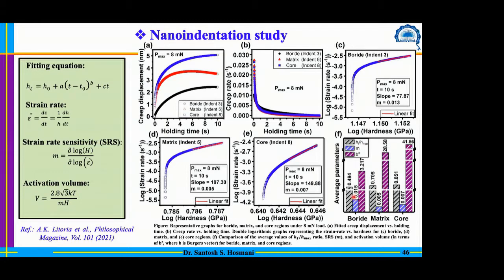Why? Because how is that strain rate sensitivity useful for us? During application, we may have different sliding speeds. In some cases the sliding speed is slow, in some cases it is faster. The higher the strain rate sensitivity, the greater the possibility of a rise in hardness due to the strain hardening phenomenon. That actually helps us improve the wear resistance, and we also observed that during our wear study at different sliding speeds. So the high strain rate sensitivity of the boride is advantageous, especially in tribological applications.